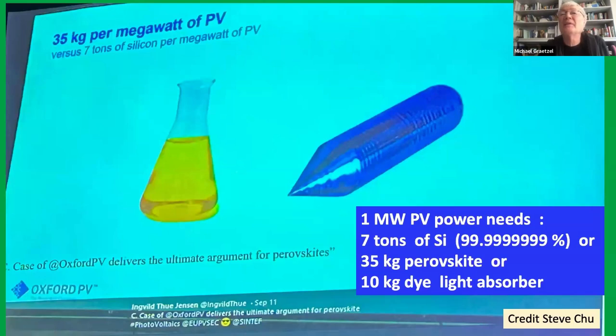One of the emerging technologies is the dye-sensitized cells and perovskites. As you can see, silicon uses a lot of very highly pure material. For 1 megawatt installed, you need 7 tons of silicon, and 1 megawatt of peak power is not all that much. But perovskites and dye-sensitized cells need almost a factor of 200 less. So here is the attraction from the point of view of materials, and the high purity of silicon, 99.9999999, there are 9 nines in that number.